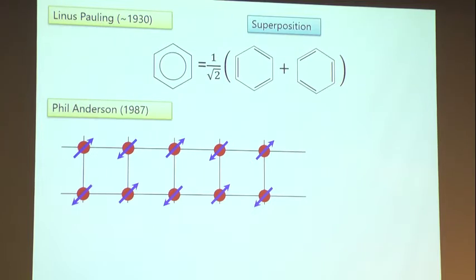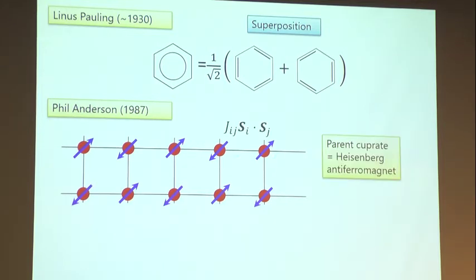So Anderson comes in 1987 and proposed that the parent compound of cuprate superconductors, a well-known insulating material called lanthanum copper oxide, forms a square lattice of a spin half degree of freedom on each site. It was well known that the parent compound of cuprate is well described by these spins on a square lattice, which interact with the so-called Heisenberg interaction. And that's mathematically written in this way. Of course, this is really a 3-dimensional structure, so it actually forms a magnetic order, and that's well established through neutron scattering and many other experimental techniques.